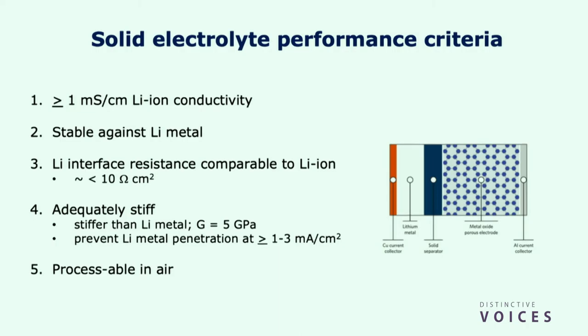Okay, so just really quickly, what are the properties? It has to conduct lithium ions as fast as a liquid can at room temperature. And some do, and actually some of the sulfide materials, ceramic materials, conduct lithium ions faster than a liquid at room temperature. They have to be stable against lithium metal if they're going to enable lithium metal batteries. They have to have low interface resistance between the lithium metal and the solid electrolyte. They have to have adequate stiffness so they can squash those dendrites. And ideally, they're processable in air so that the energy intensity of production is not so high.